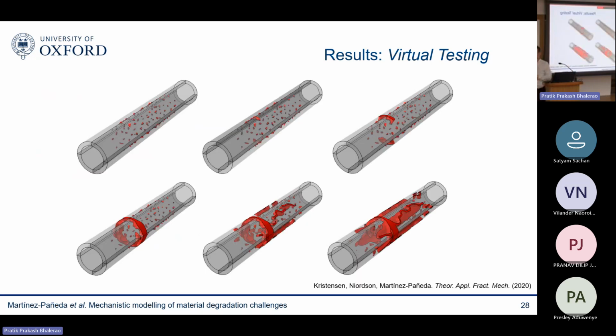And then we can subject the pipeline to in-service conditions. And as you can see here, we can see how those defects are growing, how they merge with each other, and eventually how you get the complete failure of your pipeline. So I guess the takeaway here is that these techniques are not only useful to model simple academic experiments. No matter what the complexity of your problem is, we finally have a tool that allows us to predict when hydrogen-assisted failures will happen as a function of the environment, the loading conditions, and the material.